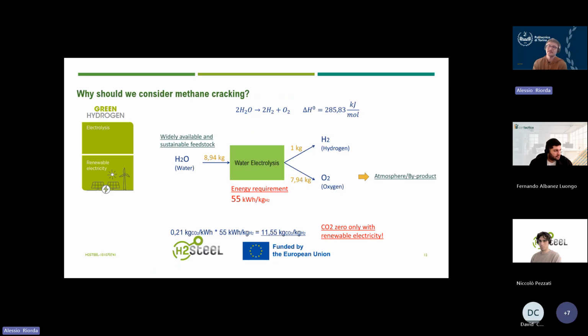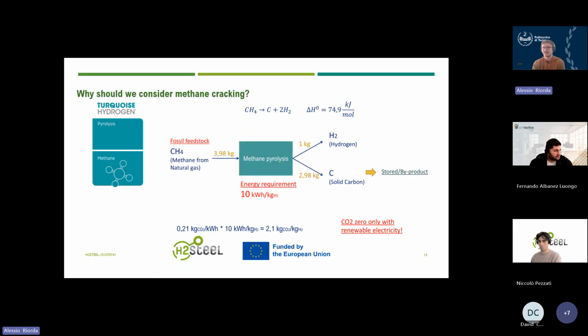But if it's completely renewable, you can decrease this CO2 amount to zero. Are there any other solutions? Yes, the one that I presented now is an interesting one, because differently from steam methane reforming, you are starting from less methane, 4 kilograms for every kilo of hydrogen, but then the carbon that you are producing is not in a CO2 form, it is not going into the atmosphere, and you do not require technology to separate it and then put it somewhere.